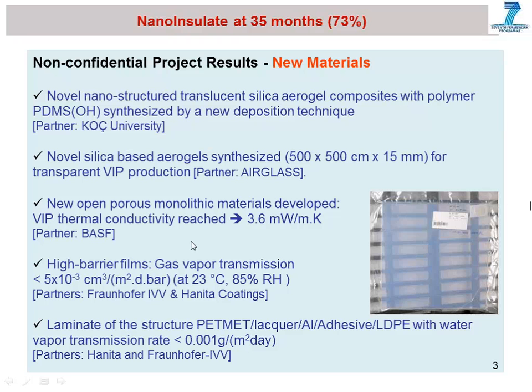And then for the opaque panels, we have new open porous monolithic materials developed. And here, quite excitingly, we've actually got an initial thermal conductivity down to 3.6 milliwatts per meter Kelvin, which is of the order that we commonly see with fumed silica. So that is a very interesting achievement for an alternative core. This will help to achieve the third objective. We obviously have robustness and lifetime as one objective. The second objective is performance of the VIPs, and the third objective is to achieve a low-cost production, which is necessary really to get widespread use in the construction industry.